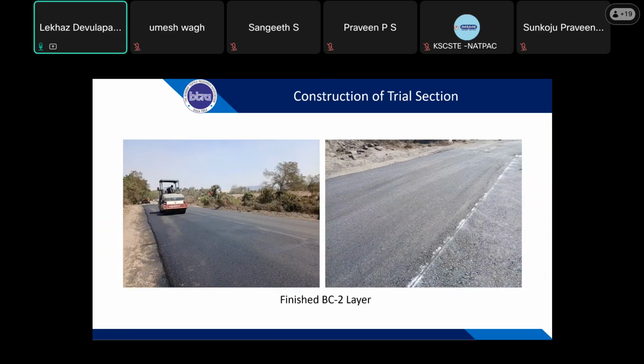So this is a finished layer of BC2 once the asphalt grid pavement has been done. On this pavement, we are going to monitor it for the next 1 year to check whether any visible cracks or rutting have appeared. We are planning to do an FWD or LWD test on this to check the modulus, and also to take cores on this to check how the performance is. We are also going to check the interface bond friction of exactly the field trial material, which we are planning.